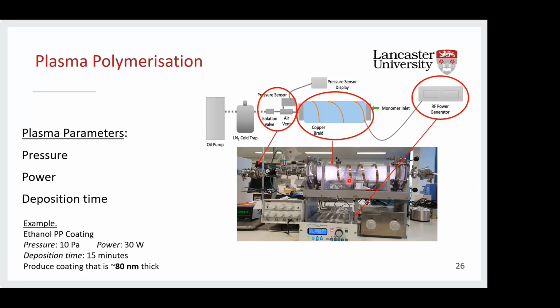At this point, you then have a plasma in your reactor, and as I said in the previous slide, at this point you have different fragmentation rearrangement reactions going on, and you're able to produce your coating. So to do this, you would place your sample here so that it sat in the plasma glow. The third and final plasma parameter that we have is the deposition time, or the time that you allow your substrate to sit in this plasma. And this is used to control the thickness of your coating.